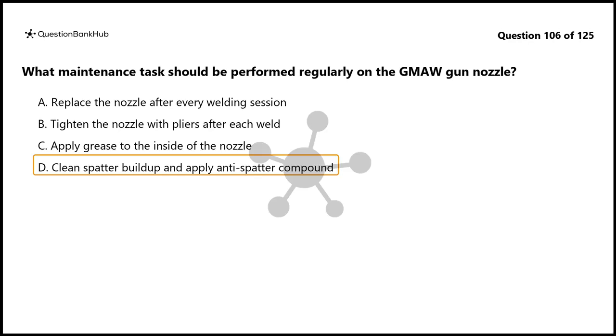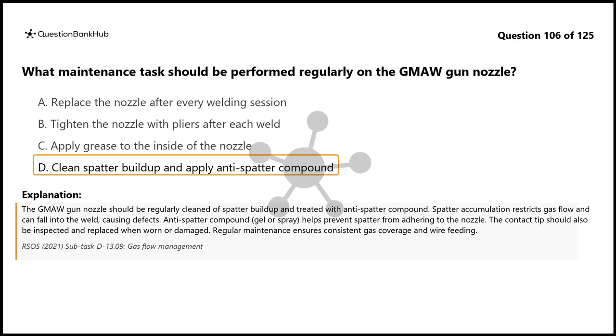The correct answer is D. Clean spatter buildup and apply anti-spatter compound. The GMAW gun nozzle should be regularly cleaned of spatter buildup and treated with anti-spatter compound. Spatter accumulation restricts gas flow and can fall into the weld, causing defects. Anti-spatter compound, gel or spray, helps prevent spatter from adhering to the nozzle. The contact tip should also be inspected and replaced when worn or damaged. Regular maintenance ensures consistent gas coverage and wire feeding.